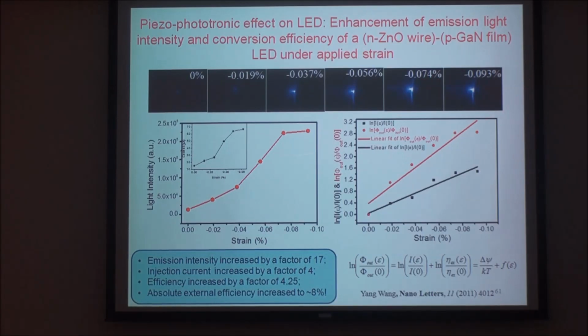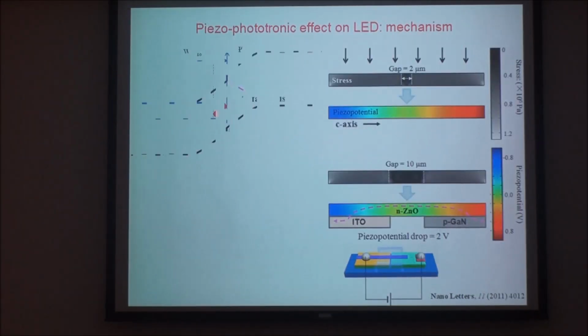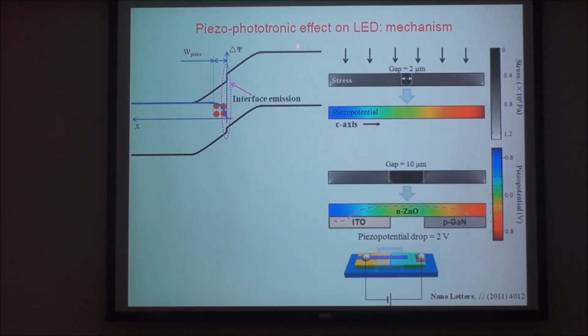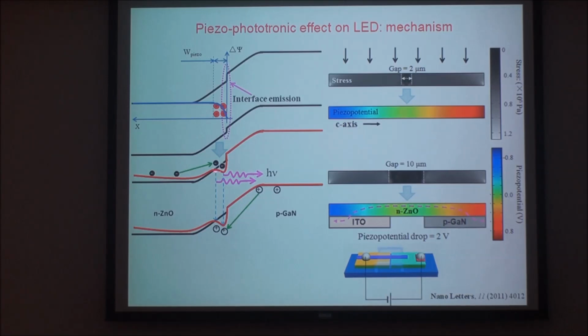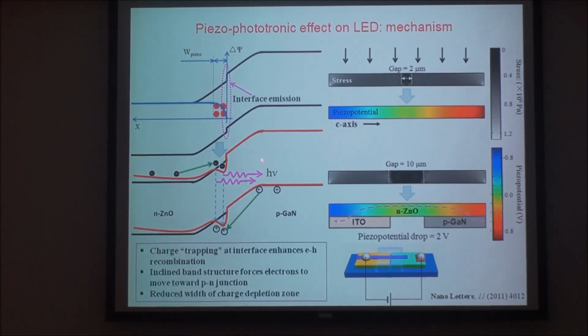This is for the LED. Why is it so? The reason is, we suggest that at the interface between gallium nitride and zinc oxide, you have ionic charge here. The ionic charge produces a local dip in the band diagram. So when the electrons move here, they could be temporarily trapped for a little longer, which enhances the electron-hole recombination rate. And this can contribute to the emission of photons. Recently, we have done a lot more work on this, applied not only to nanowires, but also to thin film. If you have a thin film, this can also enhance the emission as well. So we believe it's a rather general phenomenon.